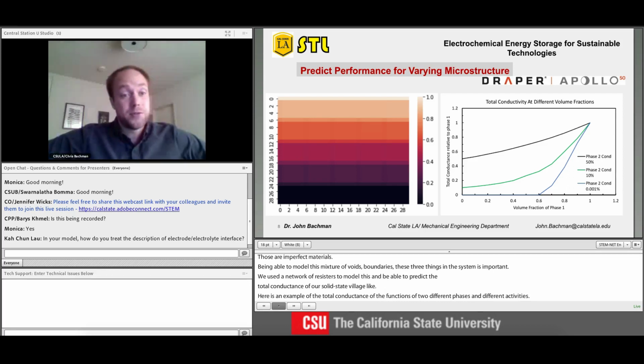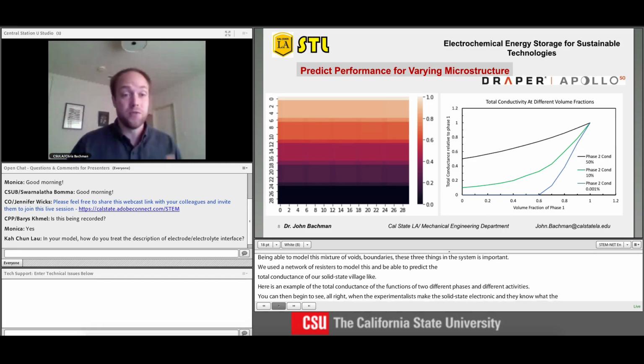and what the microstructures are, you can begin to say, okay, this is what the real cell performance is going to be under these ranges of voids, and begin to make criteria for what are acceptable percentages of voids, what are acceptable sizes for the grains, thickness of the grain boundaries, and really allows the experimentalist to go through at a much faster pace.